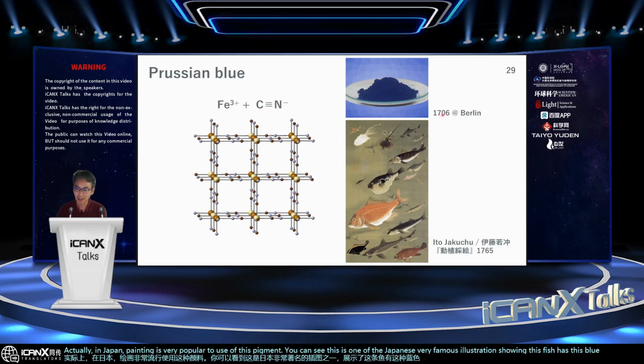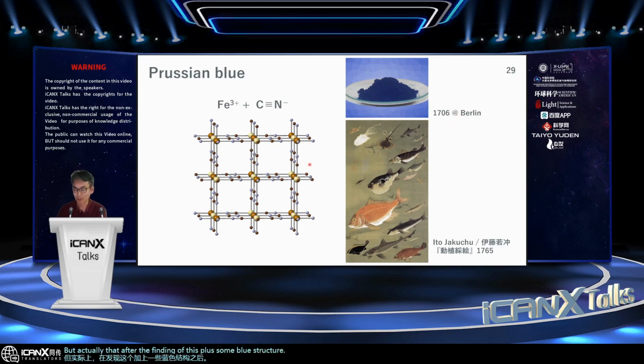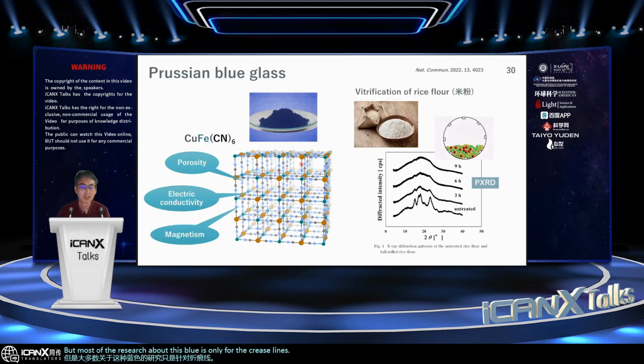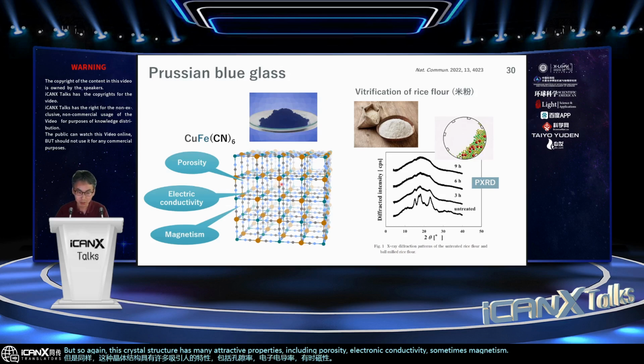But actually, after the finding of this Prussian blue structure, most of the research about Prussian blue is only for the crystalline state, because they don't have a melting temperature by heating. This crystal structure has many attractive properties, including porosity, electronic conductivity, sometimes magnetism. But heating this crystal just decomposes it without showing a melting temperature, so we were eager to get the glass state of this Prussian blue analog.